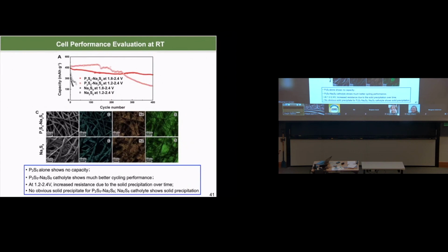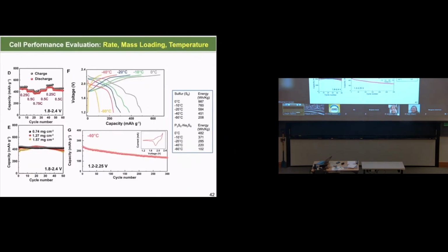I would like to show you one slide right here, because one of the reasons we want to work on the catholyte material is that we try to use it for low temperature application. Because we avoid this cyclic solid-liquid-solid phase transition, we boost the kinetics of the battery material for low temperature application. I especially want to bring your attention to this capacity versus cycle number plot. This is at minus 40 degrees Celsius. Using this material, we're still able to achieve a very stable cycling performance over 300 cycles here.